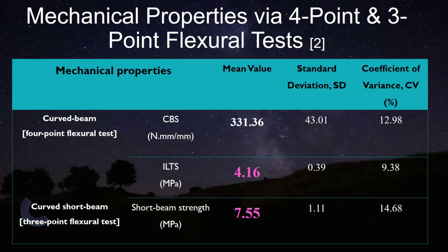Now, probably you have seen that I did not include that image over there. Probably if you go back to my article number 2, which I put inside the reference section. This is a curved beam actually. This is the first time we have done this curved beam test on the biofiber. So we tried to figure out the interlaminar tensile strength from the 4-point bending, flexural bending, and that's a curved beam. And we found 4.16 megapascal as its mean value. That is also adhering to the standard.